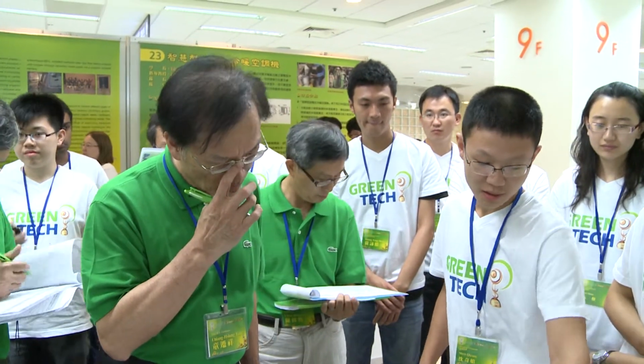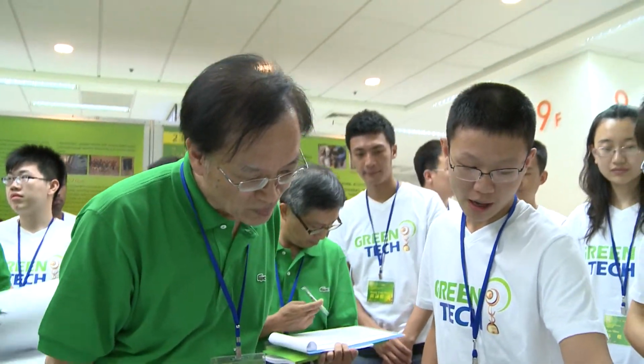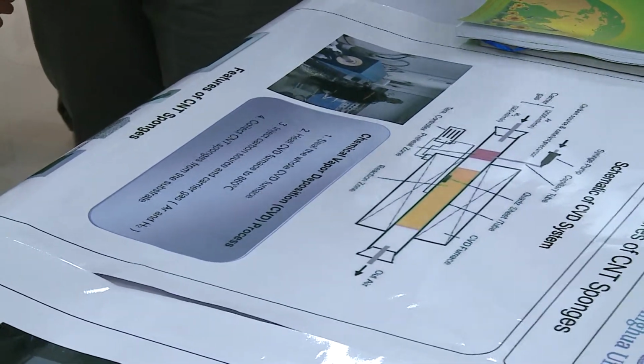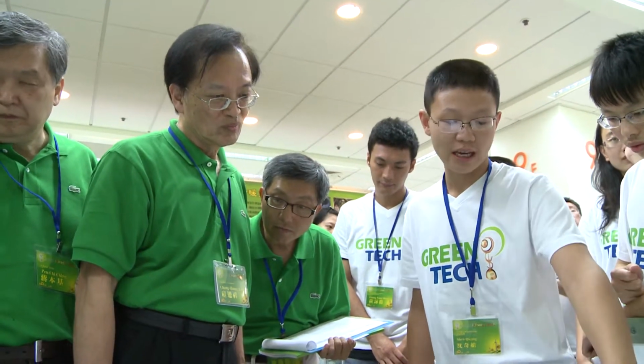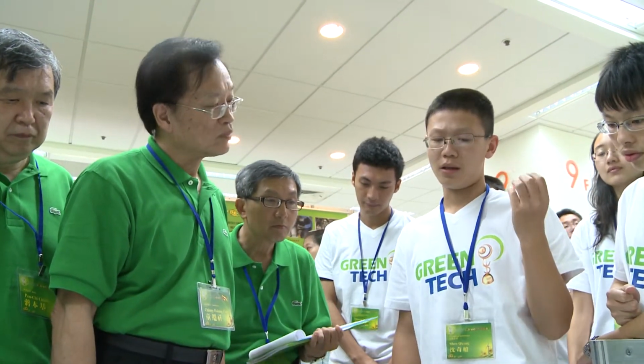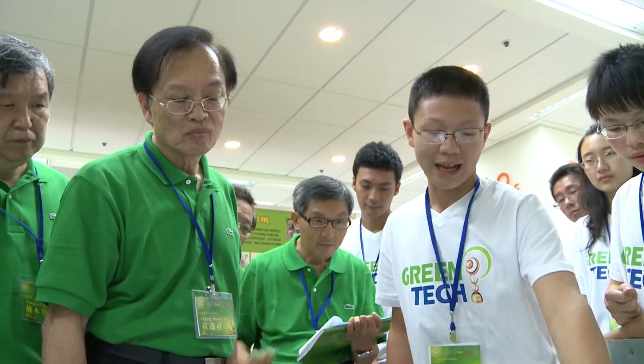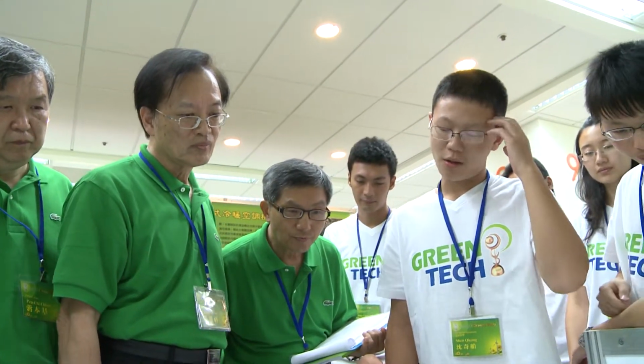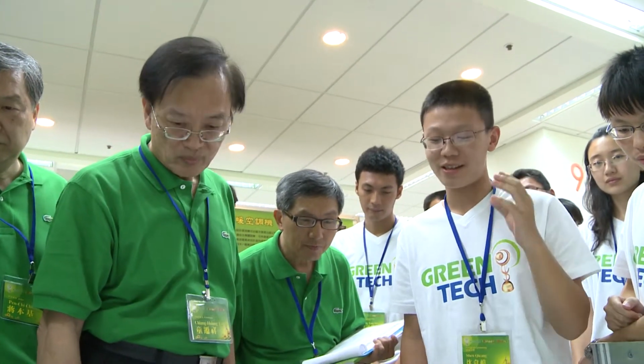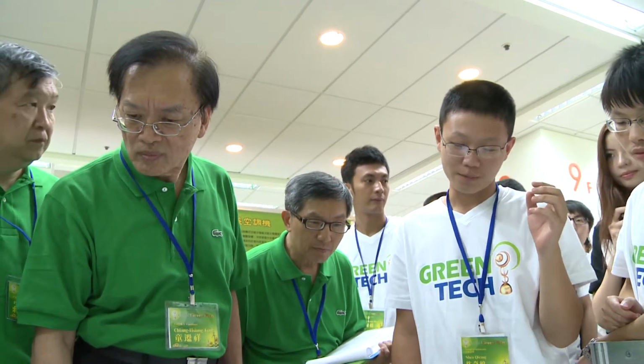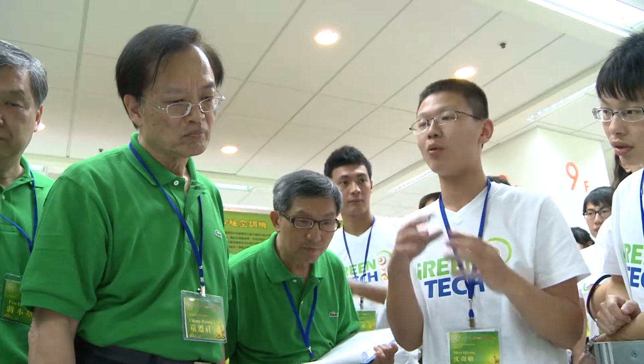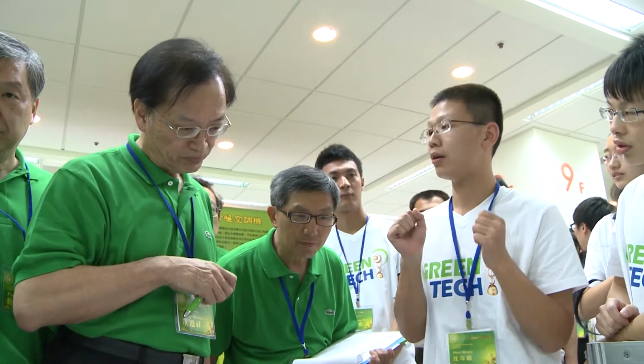During the process, first we check the device and seal the furnace. Then we heat it to about 860 degrees Celsius. After that, we inject the carbon source. The carbon source is chlorobenzene mixed with the catalyst precursor, ferrocene. I forget how to pronounce it. At last, we collect the CNT sponges from the substrate. The substrate is a quartz sheet, because it can endure the high temperature.